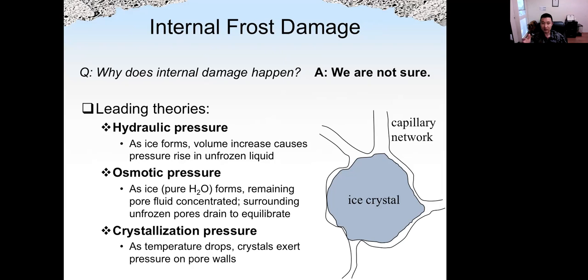So let's look at the internal frost damage, which occurs in the cement paste. There are several theories which may help to explain why we have internal frost damage. Exactly which one is dominant, we do not really know. These are the potential contributing factors for the internal frost damage of concrete. The first one is the hydraulic pressure. So when ice forms, the volume will increase because the density of ice is lower compared to the density of liquid water. So the volume of ice will increase. That will cause pressure rise in unfrozen liquid in surrounding areas. For example, here we have an ice crystal formed here. The water surrounding the ice will have a high pressure because the ice volume will expand. So that may cause the concrete to crack.